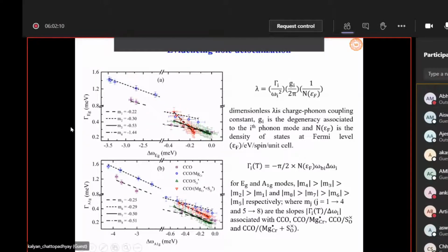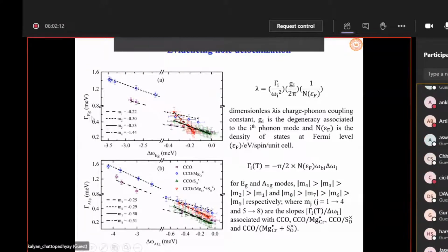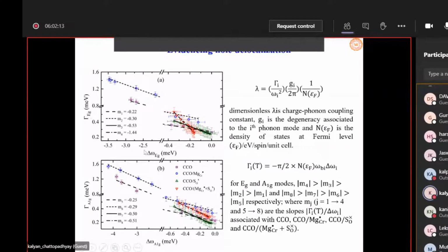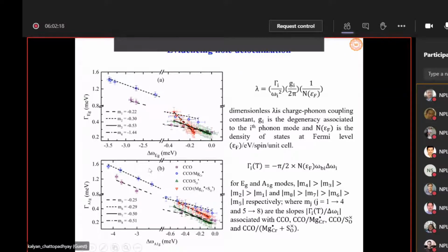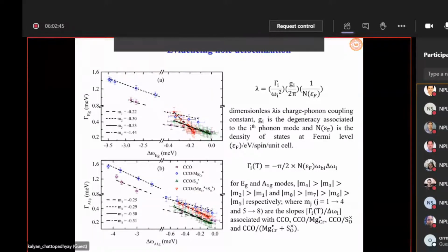This N(EF) is possible to obtain if you plot gamma, the FWHM of the Eg mode, against the change in frequency or peak shift, or for example the A1G mode with shift in frequency. Then from the slope of these plots, you see this experimental plot with the statistical variation, it is possible to calculate the density of states N(EF), and it has been done. So this is basically a non-destructive technique to determine the carrier density without doing temperature dependent Hall effect and other things, by using the temperature variation of Raman spectroscopy.